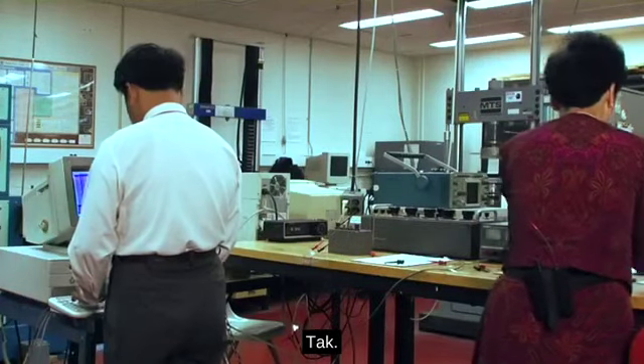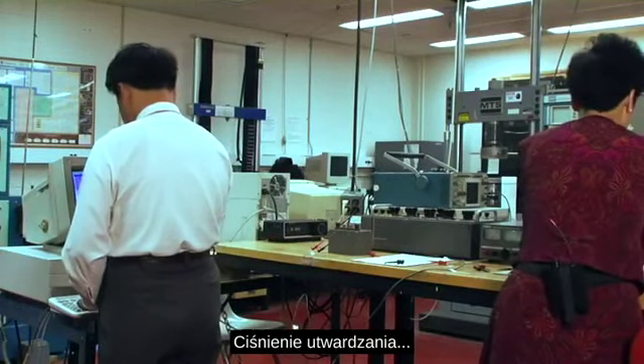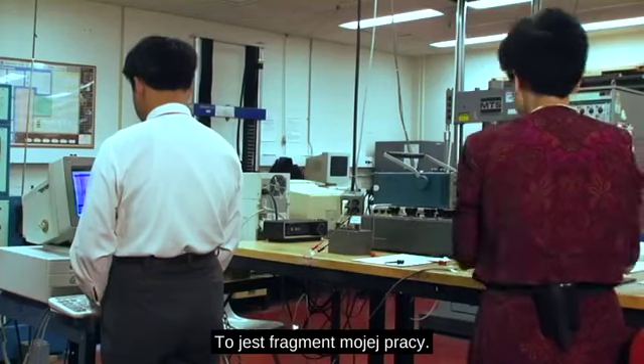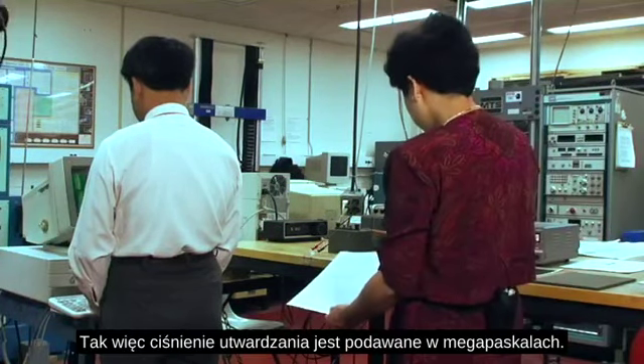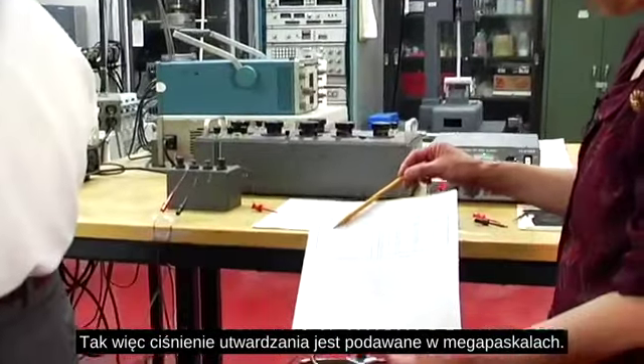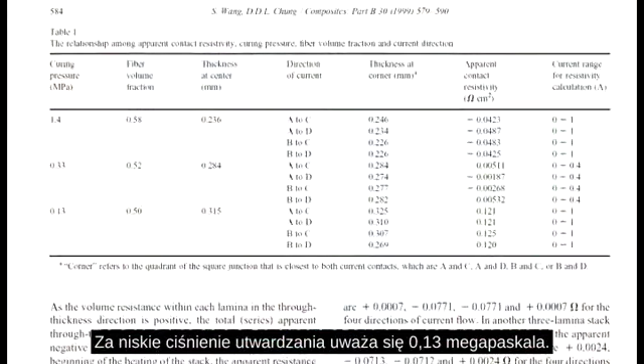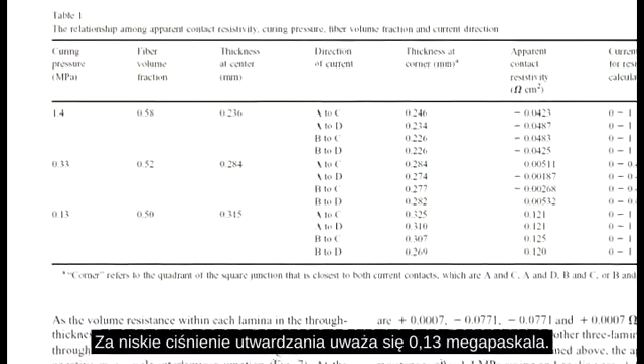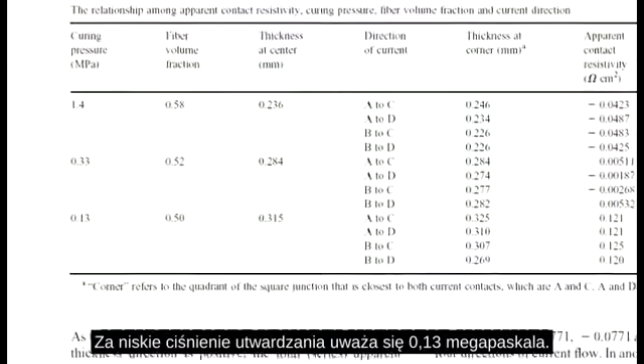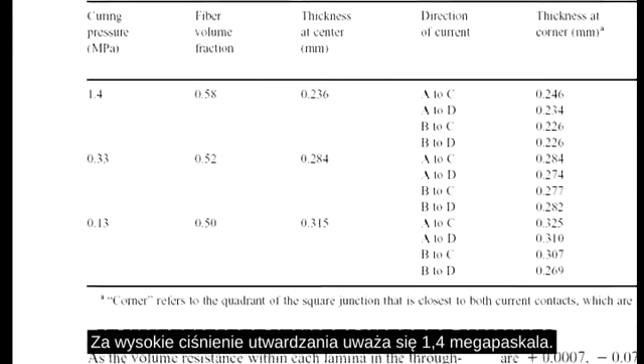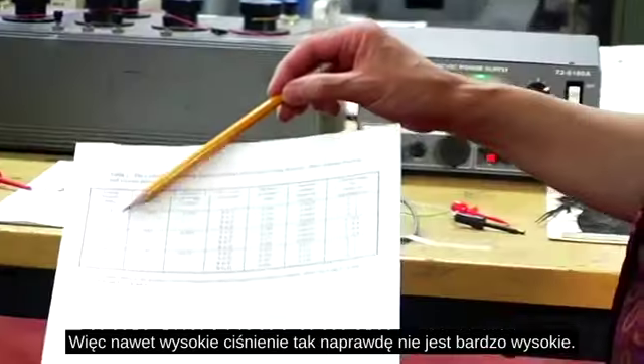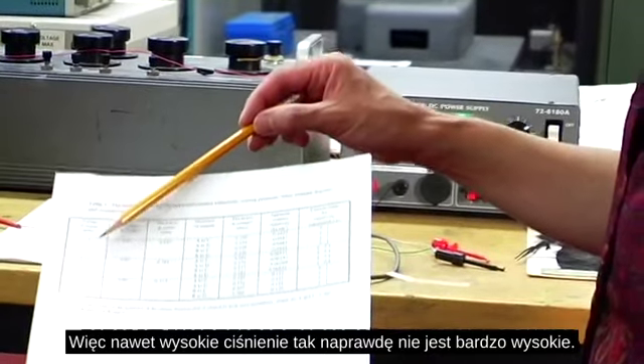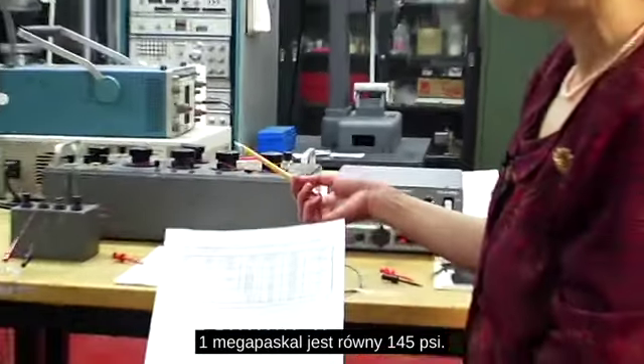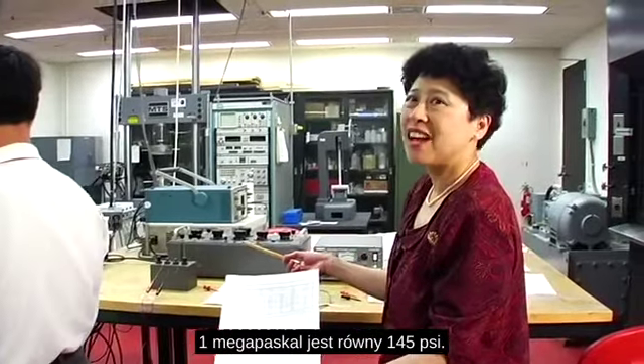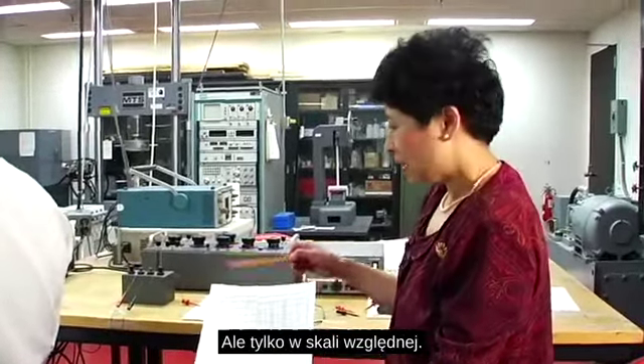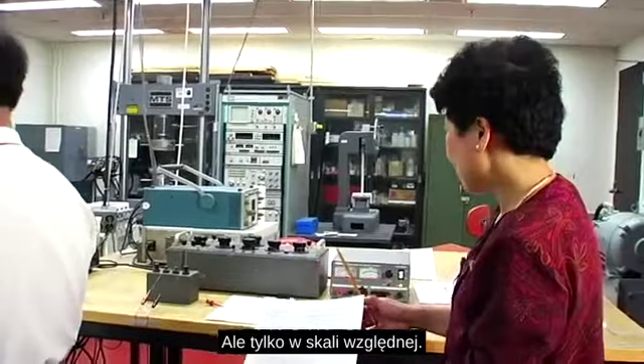Yes, the curing pressure, this is from my paper. This is curing pressure in megapascal. And 0.13 megapascal is considered a low curing pressure. 1.4 megapascal is considered a high curing pressure. So even high is actually not a very high pressure. 1 megapascal is the same as 145 psi. So it's not very high pressure, but just on a relative scale.